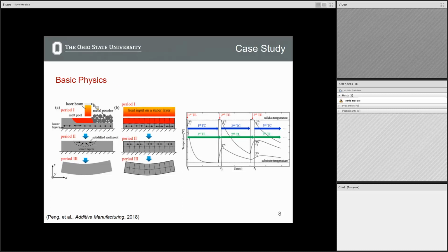I think one detail that the paper didn't go into is what is the state of stress in the melt pool. And it's pretty safe to assume that the state of stress in the melt pool, relative to the state of stress in the solid material, is 0. You can think of this if you were to take your finger and put it through the melt pool. I wouldn't recommend it, but it would essentially have no stress built up in terms of the resistance you get if you try to put your finger through a piece of metal, right? So very, very different. So we have essentially 0 stress in the melt pool, and then as soon as it starts to freeze, then you have stress accumulation.